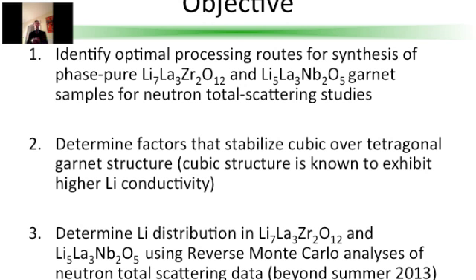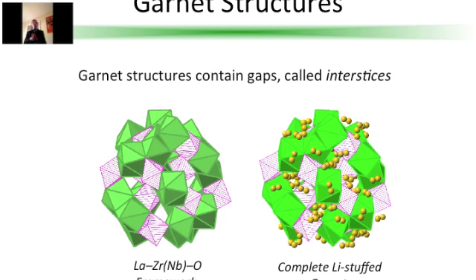Finally, I wanted to determine the exact distribution of lithium atoms in lithium lanthanum zirconate and lithium lanthanum niobate using a technique called reverse Monte Carlo analysis on neutron total scattering data, which I will go into shortly. So these were the three tasks at hand.